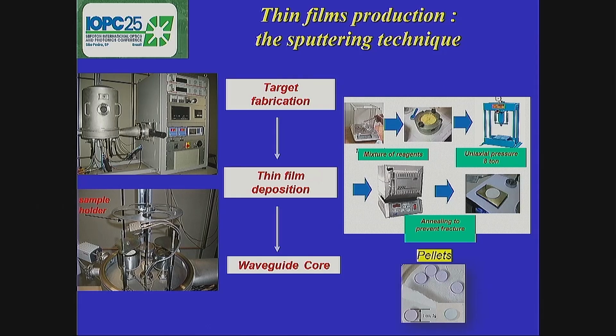And here are the steps that we use for the preparation of the targets. Most of the targets are prepared by us, not only those of the hosts, but also the smallest ones that are here. The pellets are normally made of rare earth oxides, and they are used to dope our thin films.